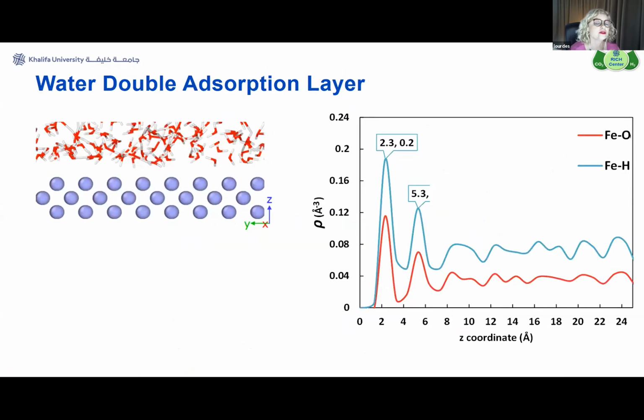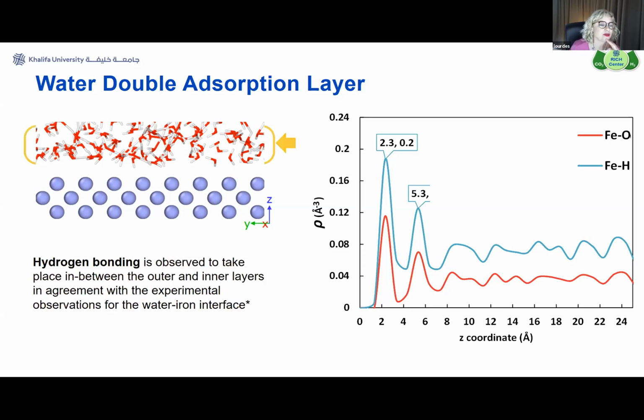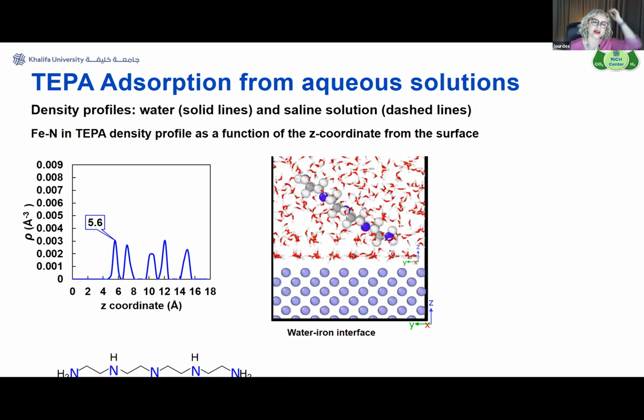Then we move on to the case of having water. And as we saw in the previous talk with Frederick also, we can observe here a very strong water double adsorption layer on top of the iron. And this is actually in agreement with the experimental observations for the water-iron interface. So this is very interesting because we will see that this actually affects the adsorption of the corrosion inhibitors that we have. So let's move on to the adsorption of TEPA when we have water solutions.